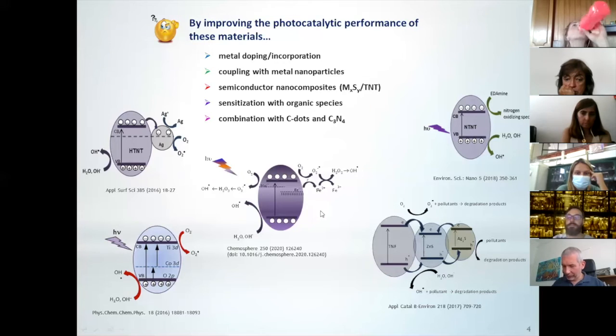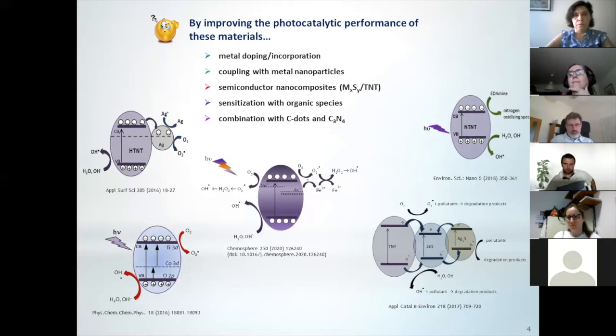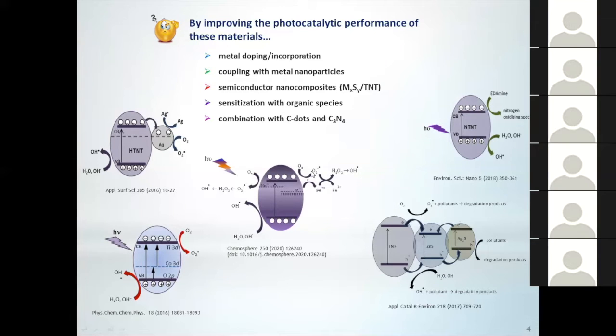these particles probably 10 or 20 times, and we always had pink color, very pale but pink color. This was a kind of pink period in our lab. For months, we were not able to prepare white titanate nanowires. Okay, so going directly to the point, what was the problem?